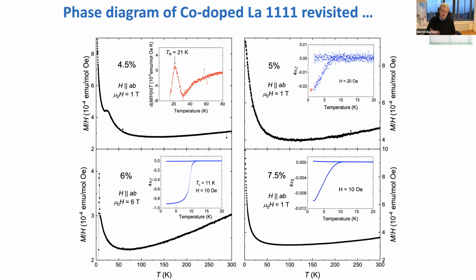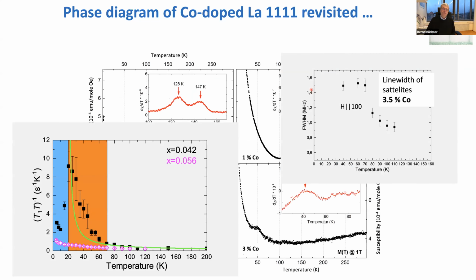So we also used NMR to study the properties, and that confirms what you get from the macroscopic properties. You see this very strong change of 1/T1 when the magnetic order is still present, and then it disappears, and we lose the long-range order. Looking at the satellites, we can also determine the structural phase transition.